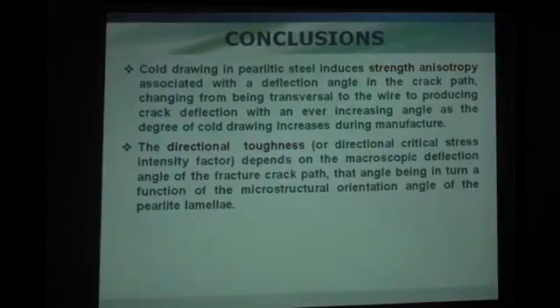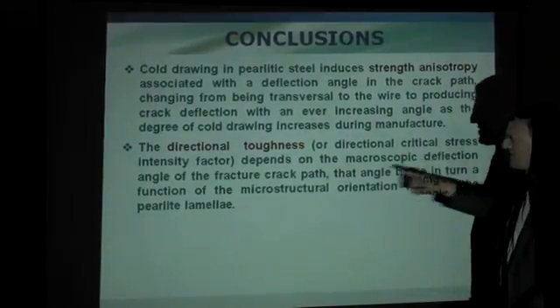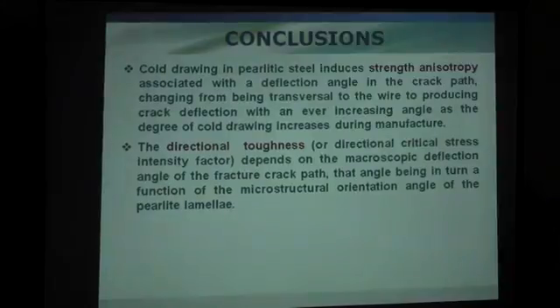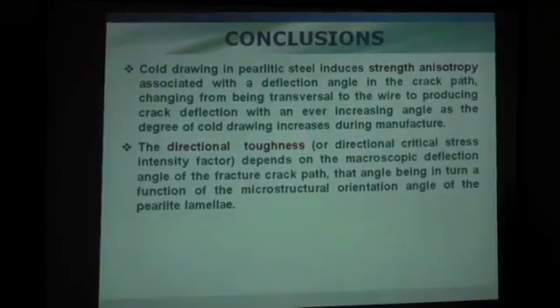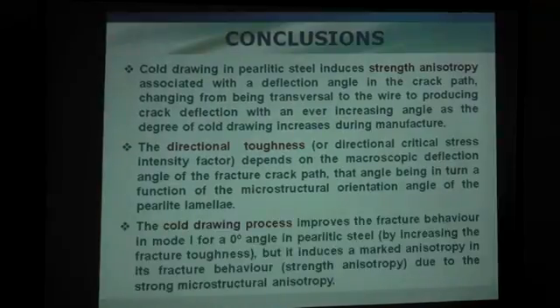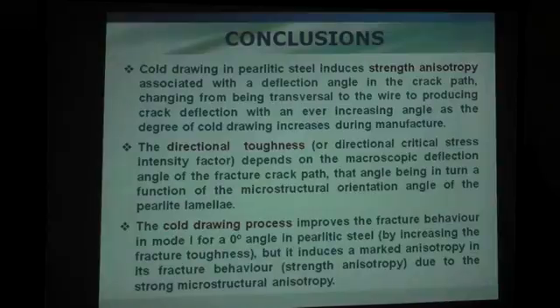The directional toughness or directional critical stress intensity factor, or directional energy release rate, depends on the macroscopic deflection angle of the fracture crack path. That angle being in turn a function of the microstructural orientation angle of the pearlite lamellae, as a consequence of the microstructural orientation induced itself by manufacturing process by cold drawing. Then cold drawing is beneficial. We know long time ago it increases the yield strength.